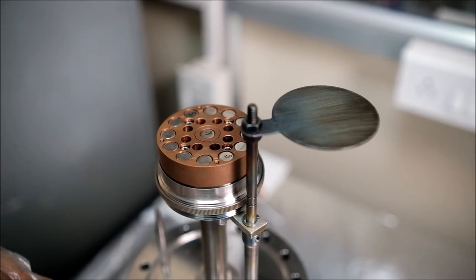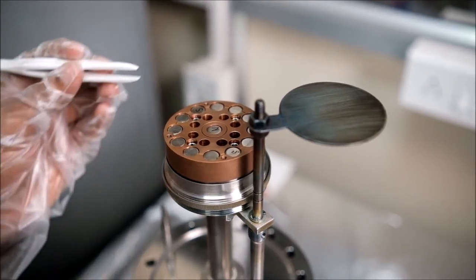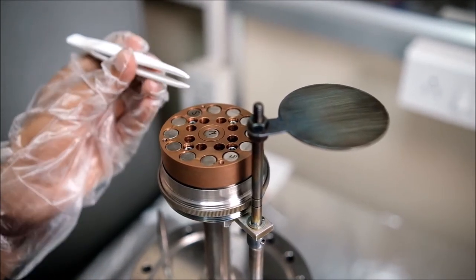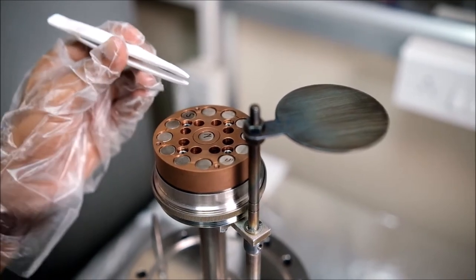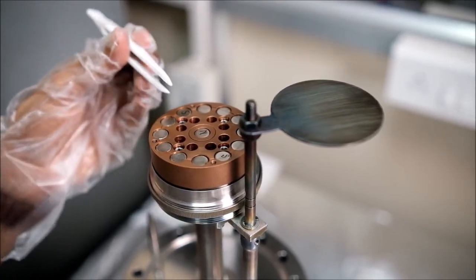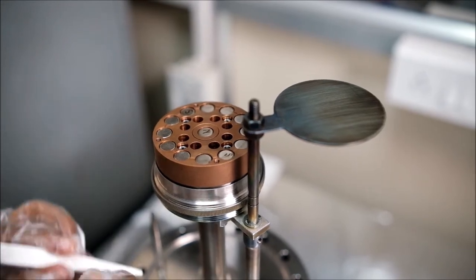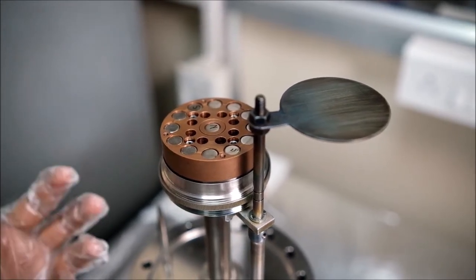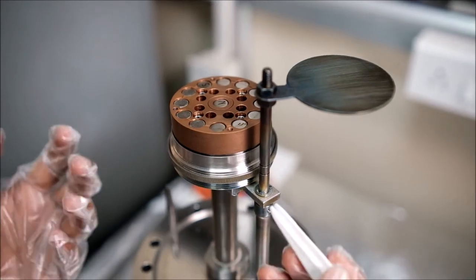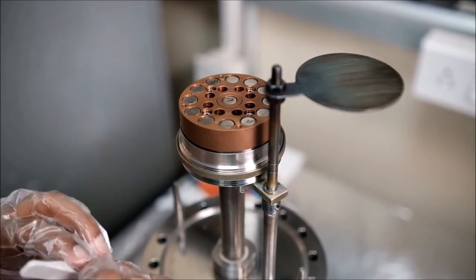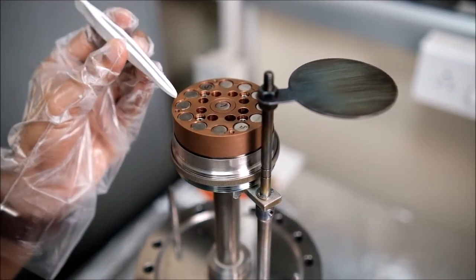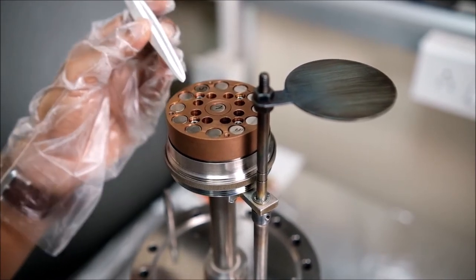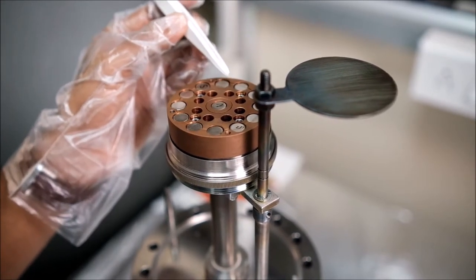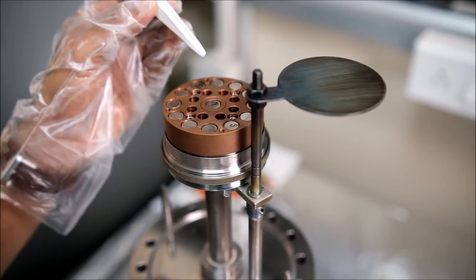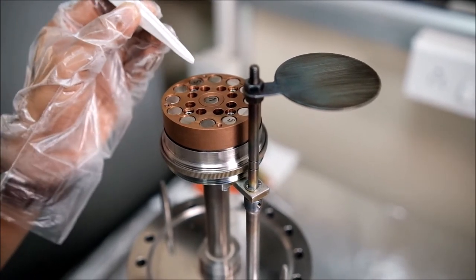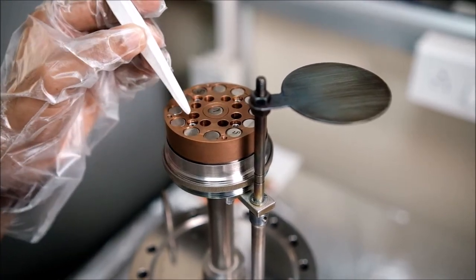This magnetic field traps the electrons, and because of the field direction, the electron path becomes elliptical. In this way, the electrons' mean free path increases, and more ionization happens from argon to argon plus. Because these electrons mostly surround this part and get most of their energy in this path, most of the argon gets ionized in this area only, and most of the sputtering happens in this part only.